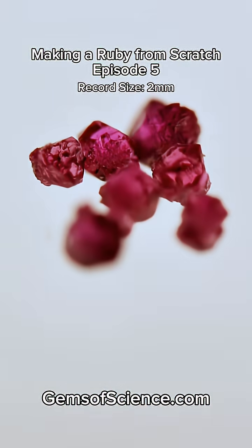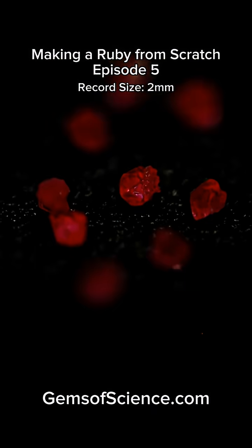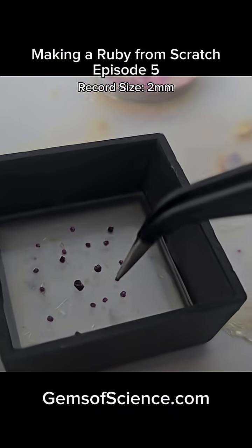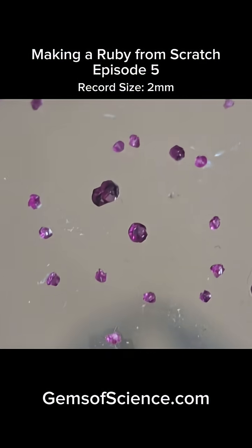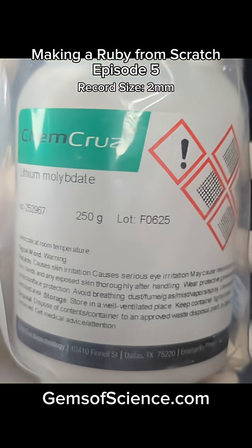They're still only up to 2 millimeters, but the quality is way higher and more uniform than before. And best of all, after a soak in water, the mix just comes out of the crucible and it's ready for another run. That went great, so it's time to start the real experiments. First, I'm going to try lithium molybdate as a flux in one crucible, and I'm going to pre-melt the fluxes to let me fit more in.